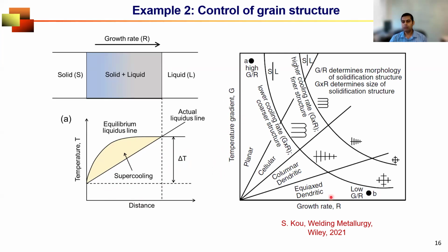This is a very well-known plot from metallurgy books, where people plot this temperature gradient, which is nothing but the temperature difference divided by the distance, the slope of this line, with respect to growth rate. Growth rate means how fast the solidification front is moving, the rate of solidification. Depending on the slope, you can identify how the solidification morphology will look, whether planar, cellular, columnar or equiaxed.